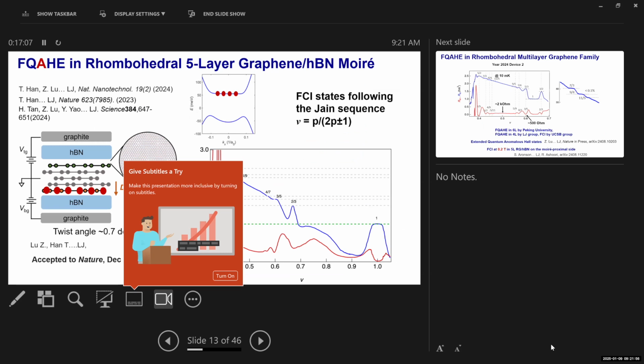So the setting is like we have a 5-layer rhombohedral graphene like this, and we control the twist angle between the top hBN and the top layer of graphene to be close to 0 degree. That 0.7 degree is unintentional - we think it doesn't matter if it's 0 or 0.7 because there is a lattice mismatch to give you moire already. And you apply displacement field, and it turns out you can push these electrons to the flat bottom of the conduction band, and physically they will reside at the layer opposite from where the moire is. But anyway, there is a moire in the system.